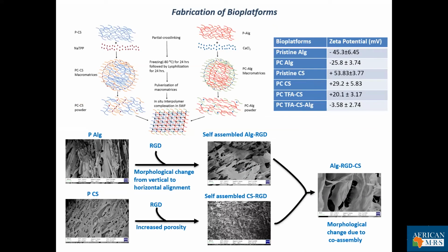So this just shows the approach for fabrication of your bioplatforms. The combination of your natural polymers, your alginate and your chitosan, with your adhesion motif to create your self-assembled model. And you can see the morphological change in your scaffold with the self-assembly of the polymers together with the adhesion motif. The increased porosity is very important, like we said, for mimicking that extracellular matrix for promoting tissue regenerative capacity.